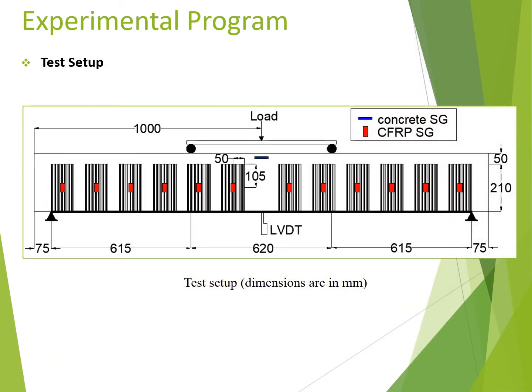The beam specimens were simply supported and tested under two-point loading tests. A universal testing machine was used to apply the load at a displacement-controlled rate of 1 mm per minute. The load was applied at the center on a spreader beam that divided the load into two equal parts, and the shear span and overhang lengths were 615 and 75 millimeters.